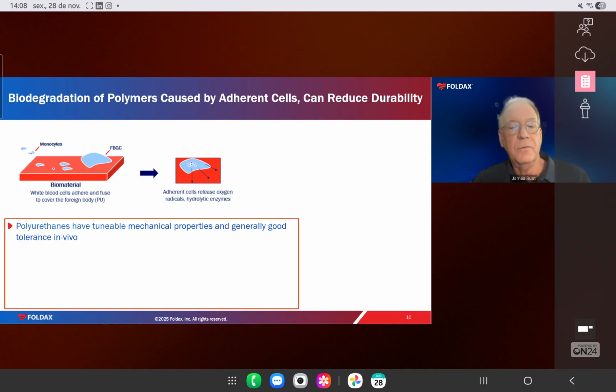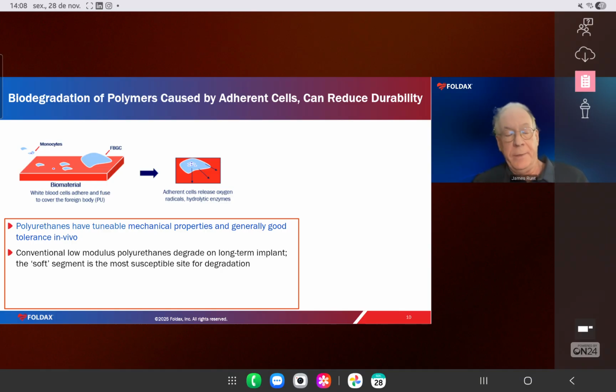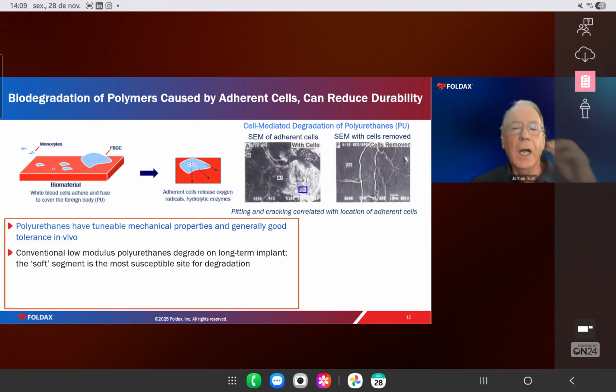Let's see if I can. I got this is next. Okay. But the situation, and you'll see this a little bit later in the presentation, a conventional low modulus or flexible polyurethanes, they tend to degrade on long-term implant. And the soft segment, the blue segments, are the most susceptible sites for degradation. I keep hitting my own buttons. There we go. And this is just one example. They're not very clear, but it's a cell-mediated degradation of a soft polyurethane. Left-hand side, it's really hard to see. What you're seeing is a scanning electron micrograph of cells on the surface of a polyurethane biomaterial. And when you take those cells off, what's underneath is a whole bunch of pits and cracks and damage, which are sites for crack propagation and ultimately failure. Right.